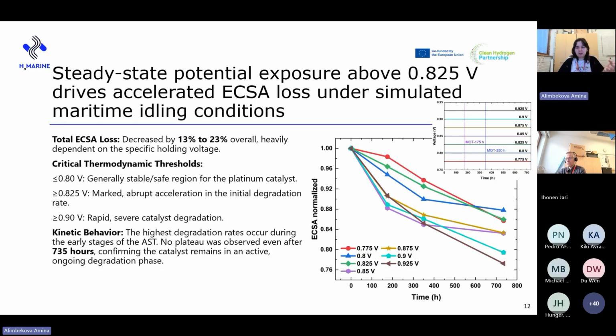This basically shows us that using our multi-channel potentiostat and a multi-single cell, we can successfully monitor the potential dependent catalyst degradation across these long times.